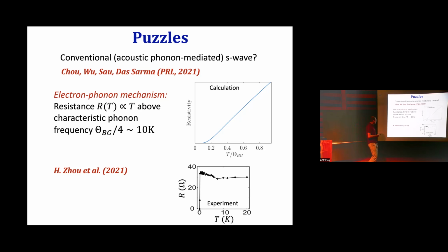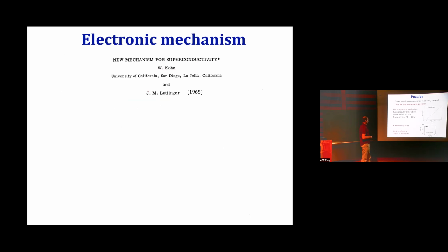Okay, and there's another puzzle which I won't go into the details of. It's more theoretical than this. It's related to the fact that we get these two superconducting states. One is a spin singlet, and the other one is a spin triplet. That turns out to be hard to square with the conventional electron-phonon mechanism. But I won't go into the details of that. So we need to consider something else, or at least that's what we believe. And there is an alternative in the theoretical literature.